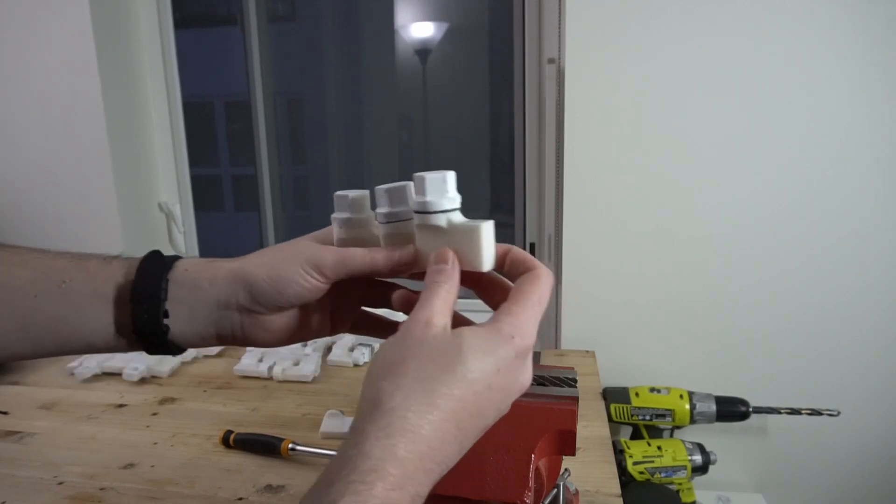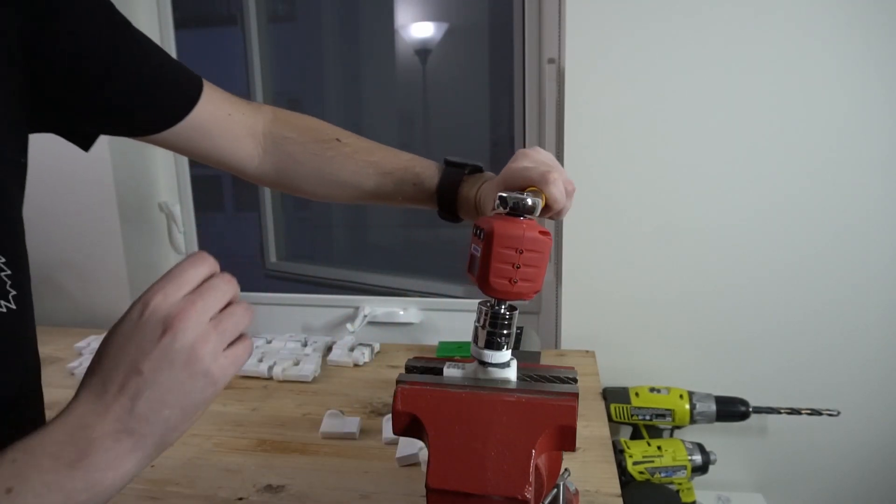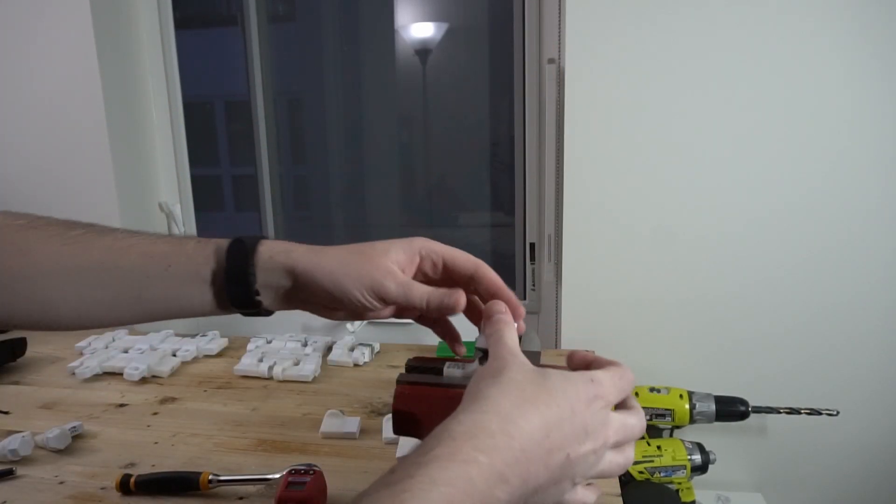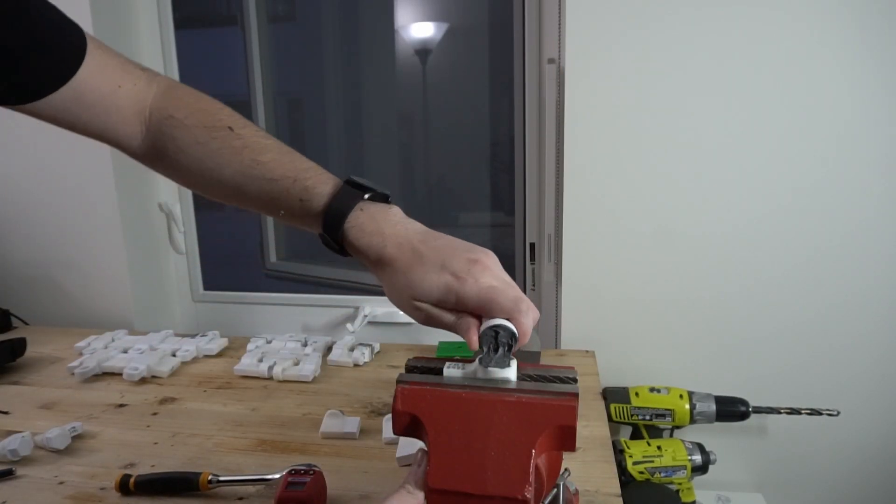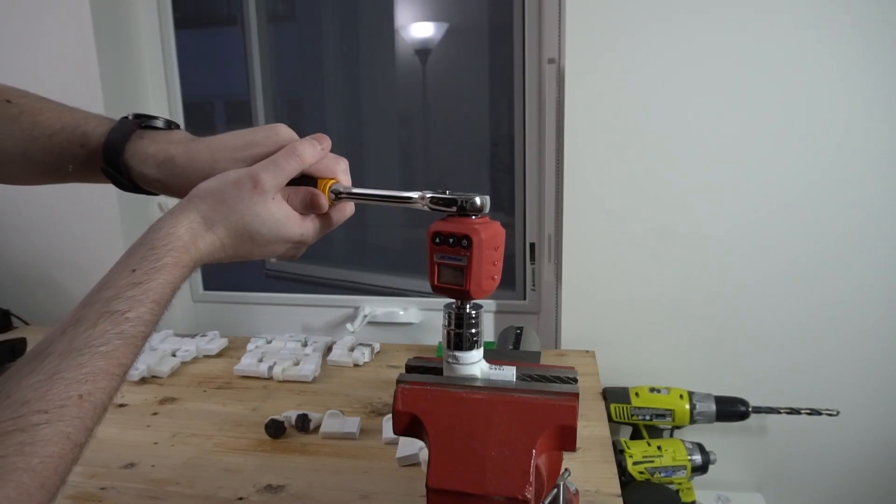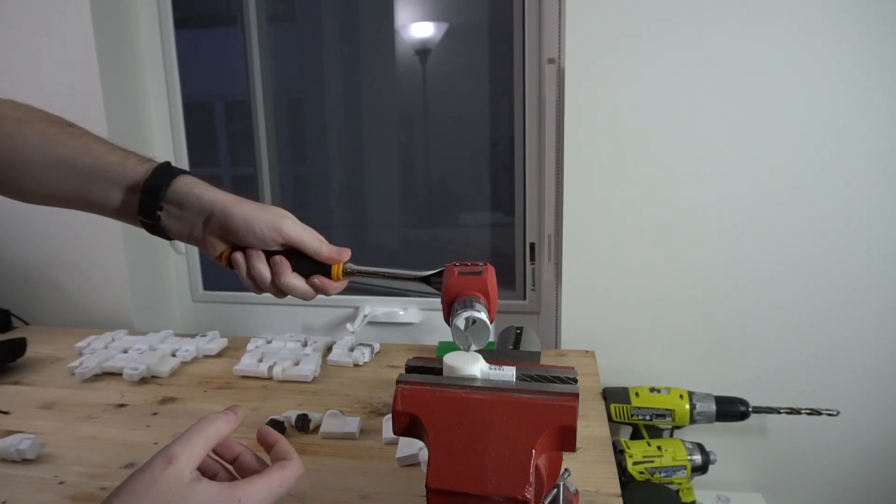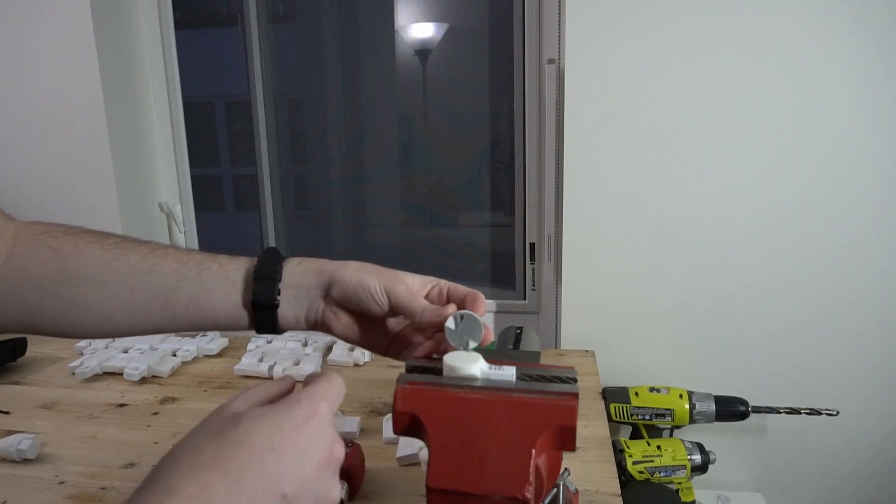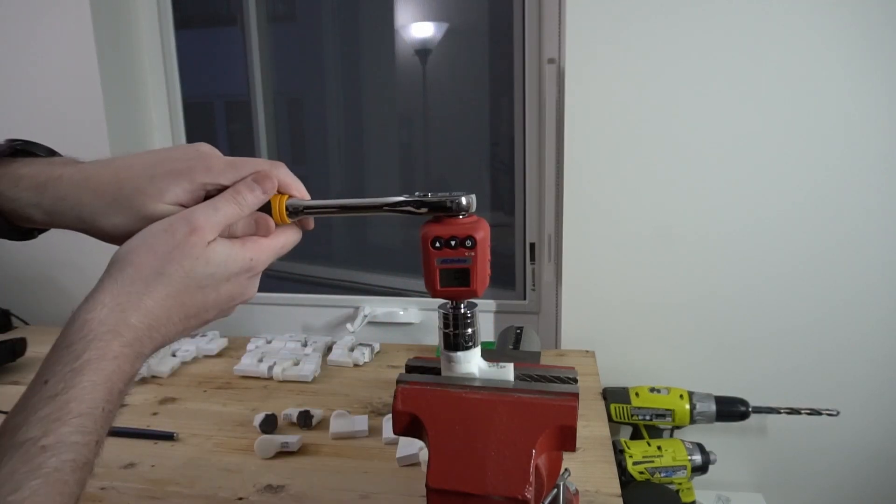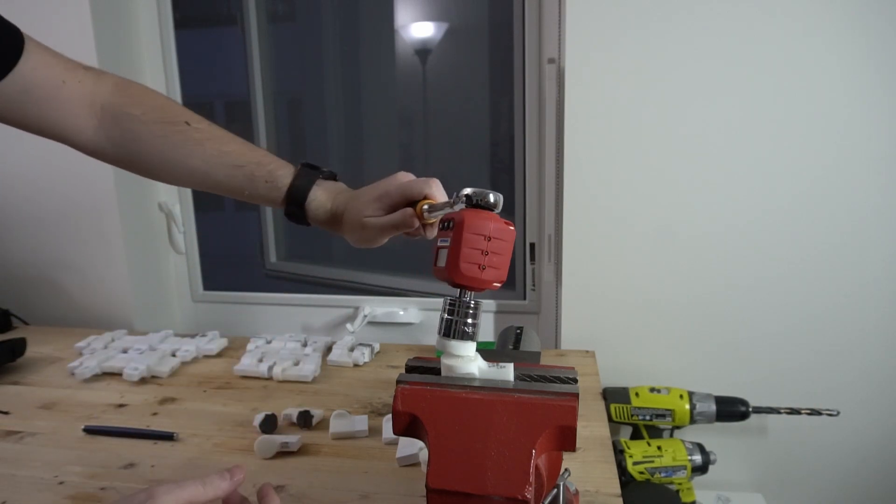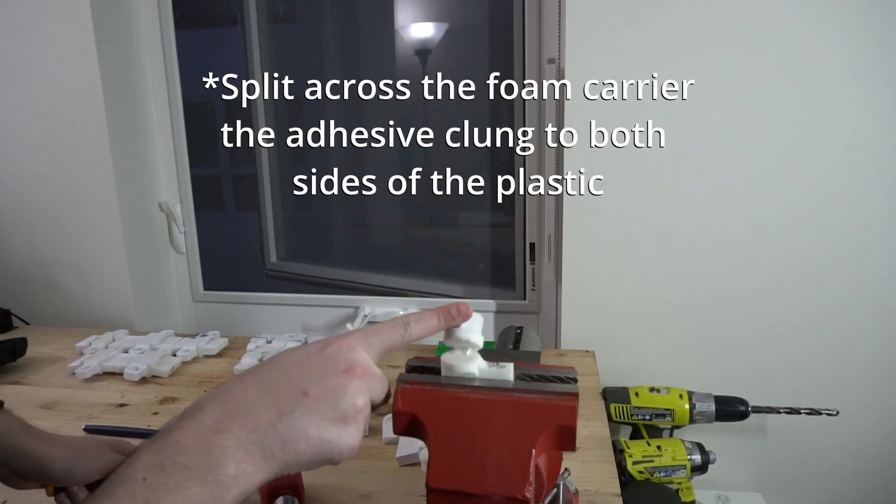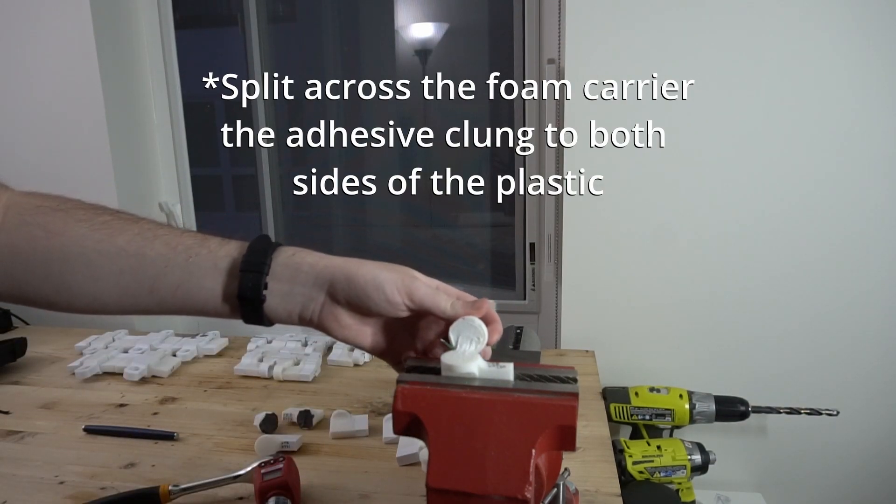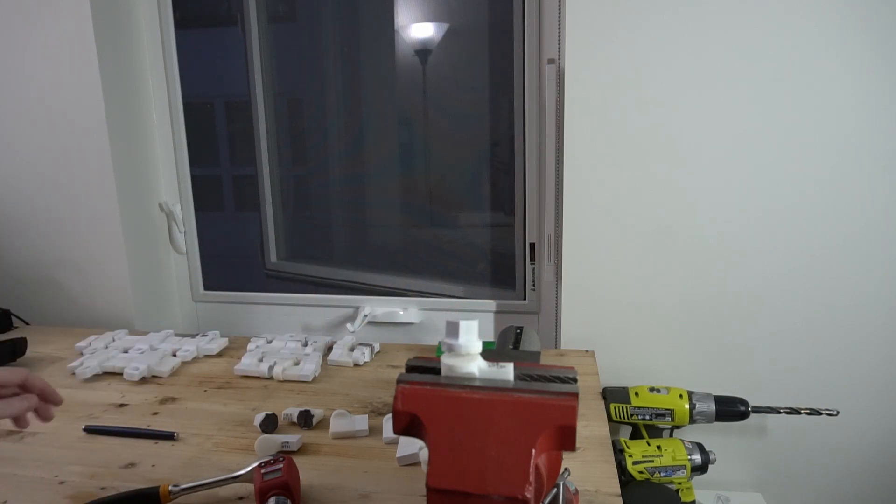After that, we have the three VHB tapes. These are pretty uneventful. They all get 0 foot-pounds, but it is interesting how they fail. So first up, VHB 5952, the black one. You can see that it actually split across, whereas the next one, the 4941, the adhesive didn't split. It actually separated off of the plastic piece. And then, finally, the LSE 160, which is meant for plastics, it also split across the adhesive, similar to the 5952, the first one we tested. It's a bit hard to see because it's white tape on white plastic, but still 0 foot-pounds.